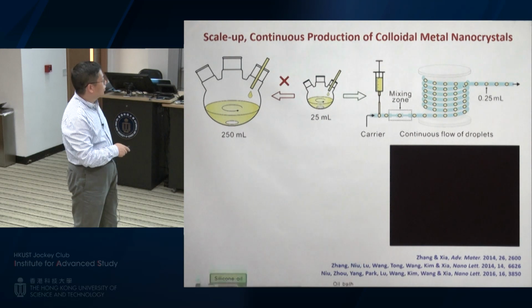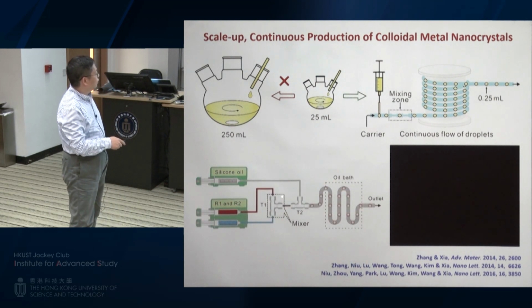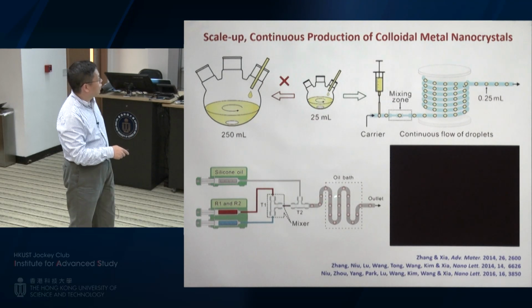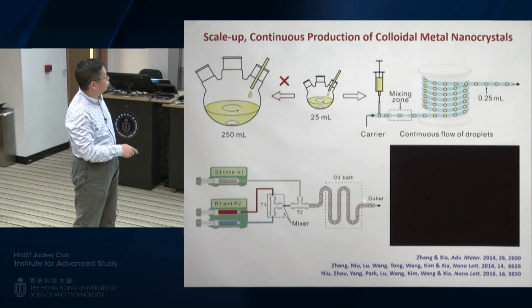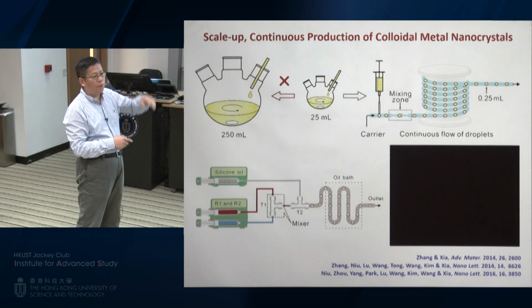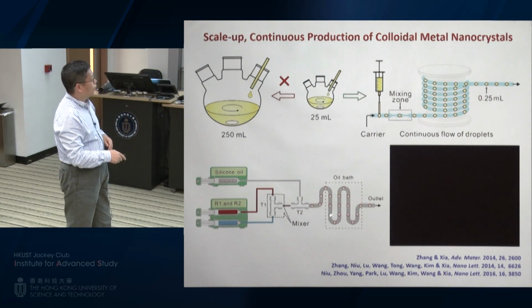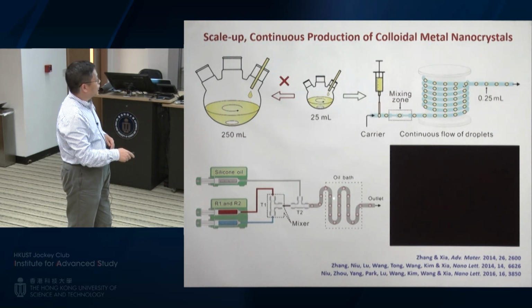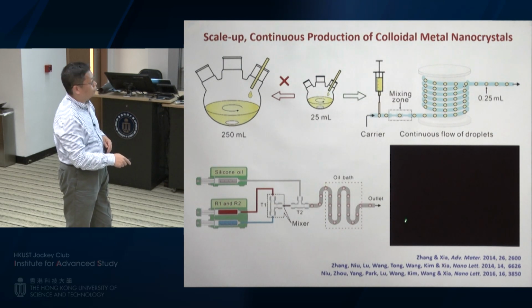So that's why we use a different approach. We reduce the reaction volume for the synthesis to make small droplets. So you're going to have a continuous flow of these droplets, and the volume could be even smaller than that. If we take reagents, carefully mix them, and disperse them into these droplets, and then let them pass through this reaction zone, basically heated using oil baths, you're going to have nanocrystals formed in each individual droplet, and then you collect them all together.